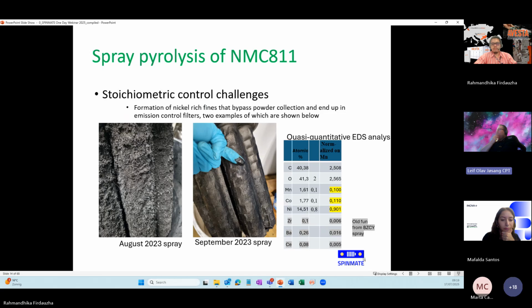So I've mentioned stoichiometric control challenges. We started by mixing stoichiometric amounts of all the cations, including lithium, sprayed it into the pyrolysis, and for the first batches, we had very poor yield, as low as 30% at the worst, and we slowly increased it. And the main reason was that we produce fines that bypass the powder collection setup and end up in emission filters. And these are two pictures from the emission filter.